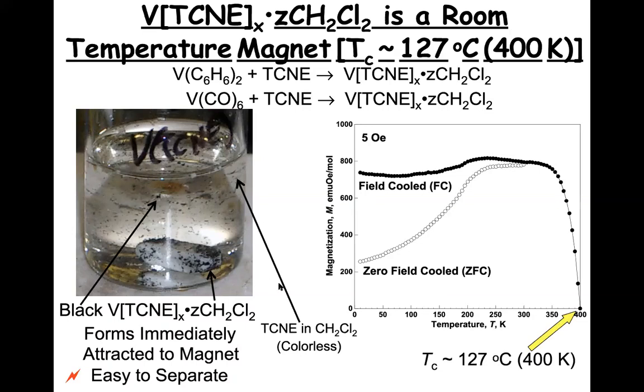And in fact, if you measure the magnetization versus temperature, this material, vanadium TCNE, now is a magnetically ordered material that orders at 400 Kelvin, 127 degrees centigrade, not 4.8 Kelvin, as I showed you on the previous slide. So now we have made a second example, and we've made more than 2 examples, of a magnetically ordered material. This material is a miserable material. It is amorphous. It's not stoichiometric, but it's magnetic every time you make it. It's also very air sensitive, so it will catch fire in the air as it's pyrophoric. But it does magnetically order at 127 degrees centigrade.